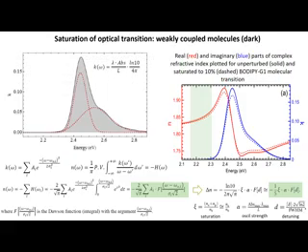We carried out a rigorous analysis of what's going on inside the microcavity if we saturate ground state absorption. First we extract the imaginary part of the complex refractive index from the absorption spectrum of the cavity material. Then we did Kramers-Kronig analysis and reconstructed the real part of the complex refractive index, and then we saturate absorption by 10% and see what's going on with the real part of the refractive index, the red curve.